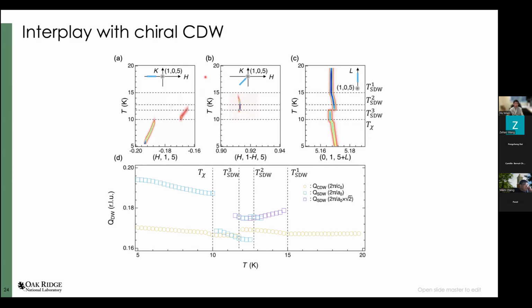Here, A and B show the magnetic, or SDW, wave vector as a function of temperature. It changes quite a bit when you're cooling down. But what is really surprising is that the CDW wave vector has a strong response whenever we enter a new spin density wave phase. When I say surprising, I mean the CDW at low temperature is already commensurate with the lattice. But once you enter a spin density wave phase, the CDW moves away from the commensurate phase to an incommensurate phase. So that's quite surprising. Another surprise is that the CDW propagation wave vector, as I'm showing here, is perpendicular to the spin density wave. So even though they are perpendicular to each other, they still show quite strong coupling.